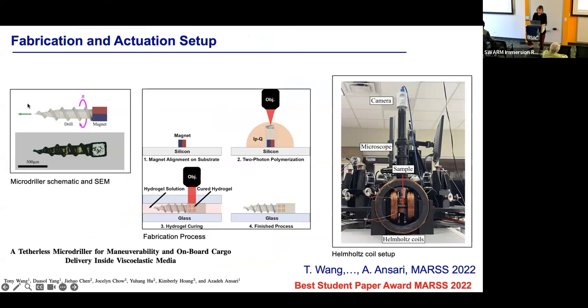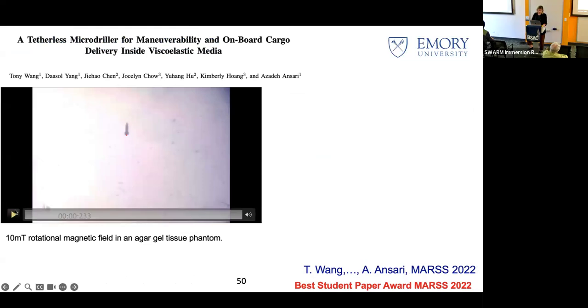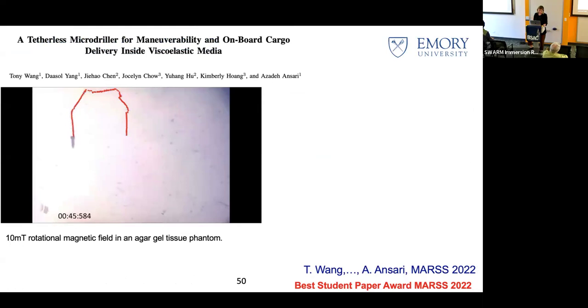So what we showed was that you can buy a 250 micron magnet and then 3D print using 2-photon polymerization a drill bit, right, on top of this magnet, which is made of a resin. And then we use a Helmholtz coil, so XYZ coils that you can see here. A grad student basically manually wound them. And when you apply quite a low magnetic field, 10 millitesla rotational field, with a joystick, you can actually control this driller to drill inside of an agar gel.